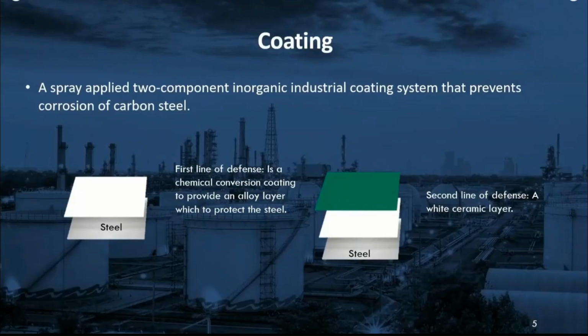And to do this, we looked at a chemical conversion system that forms an alloy layer on the steel. This alloy layer acts as your corrosion barrier to prevent corrosion. It also forms a ceramic layer over that. That gives us a little bit of additional durability, and it also maintains that alloy layer over time.